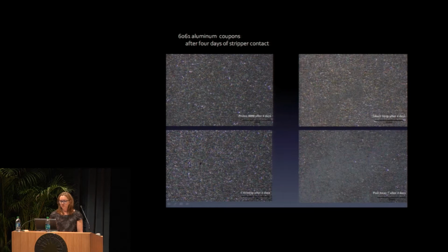But just one concern, I really pushed the boundaries and tested different coupons, and I noticed that some of the strippers were etching the surface and some were not. So that's another thing to consider. Maybe with higher PSI, we would have gotten some damage to the aluminum, but with more chemical exposure, we would have also gotten the same. So that's just another thing that I'm also exploring and doing more research on.